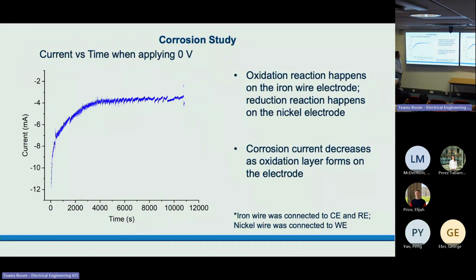So we also study the corrosion. We put the electrodes in the crucible and heat it up to 800 degrees. But instead, we don't apply any voltage. We apply 0 volts to measure the current. So that's the corrosion current. We can see, for 12,000 seconds, oxidation reactions happen on the iron wire electrodes. We can see the current is negative because the iron wire was connected to the counter electrode and the reference electrode. Nickel wire was connected to the working electrode. So we can see some oxidation reaction happening on the iron electrode, and some reduction reaction happening on the nickel electrode. So the corrosion current decreases as oxidation layers form on the iron electrode, because this increases the resistance, so the current gets lower.